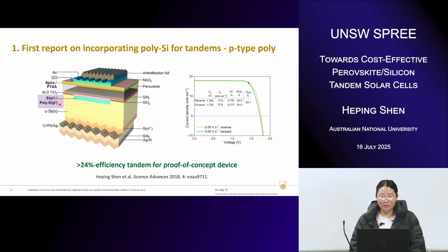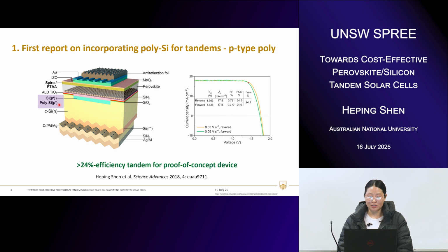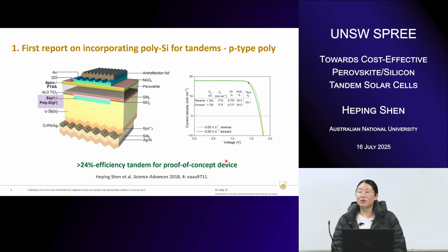So as we can see, that was the first time that TOPCon was used in a tandem, and also it is a P-type TOPCon that is used. And at that time we were able to demonstrate 24% efficiency for the proof of concept device, which is not only very high for this cell structure, but also, I believe, among the highest for any two-terminal perovskite silicon tandem based on any type of cell structure. Okay, so this is one feature: introducing the polysilicon into the tandem cell structure.